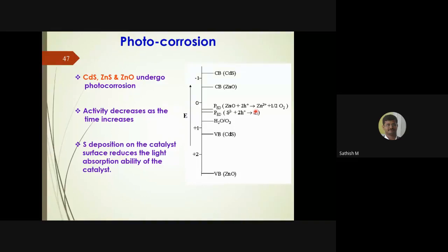So this sulfur will hinder the light absorption of the cadmium sulfide. That is one drawback. The other side is the cadmium is slowly coming into the solution. Cadmium is a little poisonous, so it is not generally acceptable. At the same time, your catalyst is also dissolving. So because of all these reasons, cadmium sulfide is not the best catalyst for hydrogen evolution, oxidation reaction or pollutant removal. So again, the stability of cadmium sulfide is questionable here.